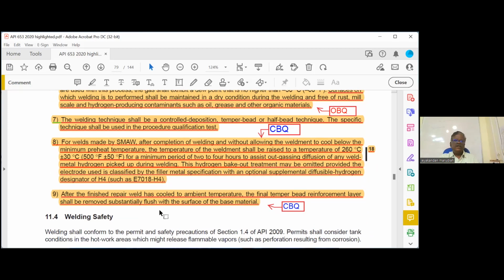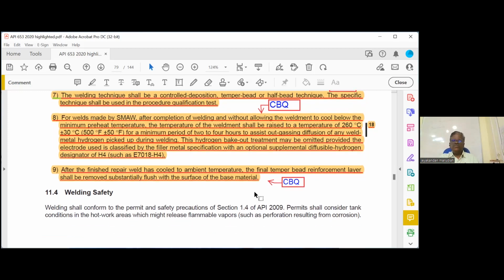Then highlight item 9. After finishing the repair, when the weldment has cooled to ambient, the final temper bead layer shall be removed substantially flush with the surface. So at the end, we have to flush grind. That is the process.